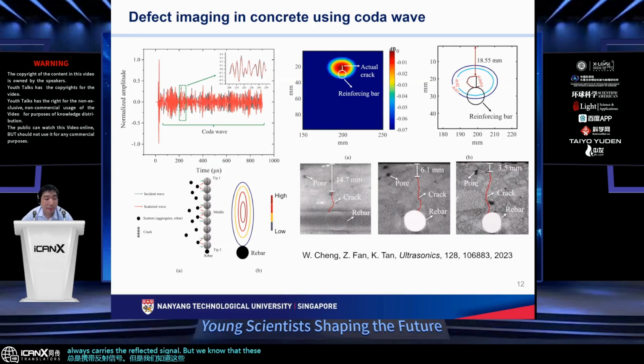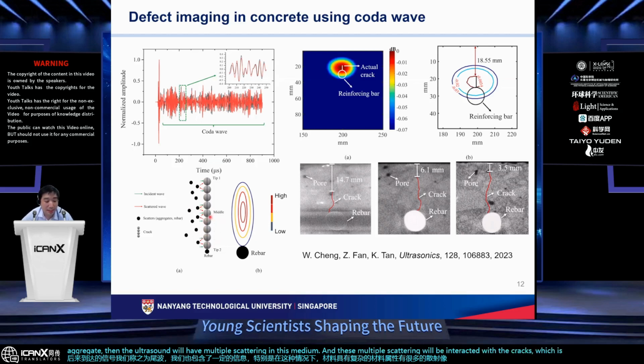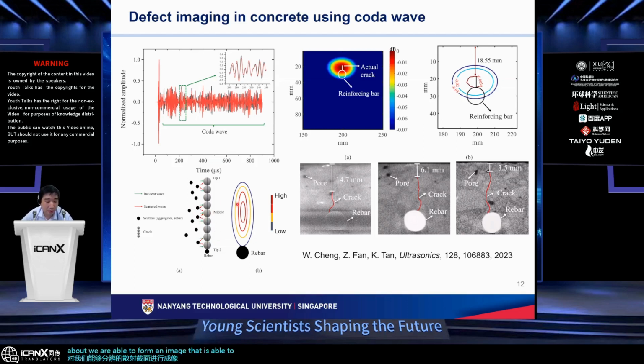But we know that these later arriving signals, which we call coda waves, also contain certain information, especially in this scenario. The material has complex properties and a lot of scatterers like aggregates, so the ultrasound will have multiple scattering in this medium. These multiple scatterings will interact with the cracks, which are basically connected with the rebar, right? So by imaging the scattering cross section, we are able to form an image that gives us the information of the crack. This information can tell us how far away the tip is with respect to the rebar. Okay, we did some work in simulation, and we also compared with some X-ray images. So this is our prediction, and the crack is highlighted by these red lines.